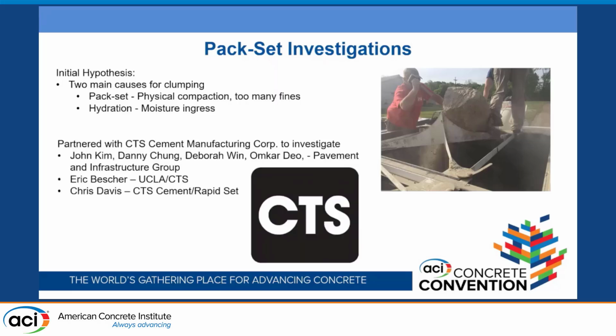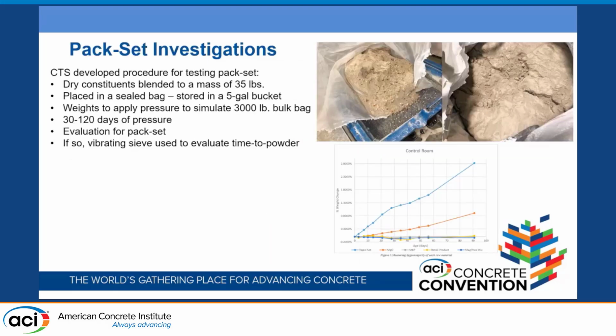We worked with CTS, some of their research group at the Pavement and Infrastructure group, and they went through and did pack set investigations. So they developed this procedure. You take your dry constituents, you blend it to a mass of 35 pounds, you put it in a sealed bag, you put the bag in a bucket, you put a weight on the bucket to simulate the 3,000 pounds of the super sack. And then you take it out after 30 to 120 days, and you see if it's pack set. If it is pack set, you put it on a vibratory sieve to see how much vibration it takes for that dry material to come apart.